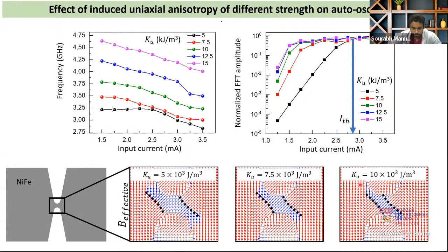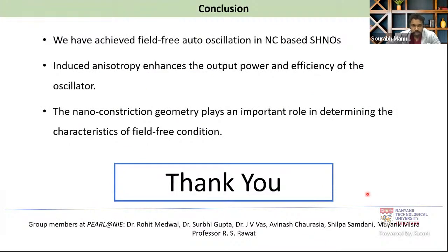So with these observations, we can conclude that we have achieved the field-free auto oscillation in nanoconstriction based SHNOs, and this induced anisotropy can actually enhance the output power and the efficiency of the oscillator, as we can tune the threshold current density of the oscillator by tuning the anisotropy. And finally, this particular nanoconstriction geometry plays an important role in determining the characteristics of these field-free auto oscillations.